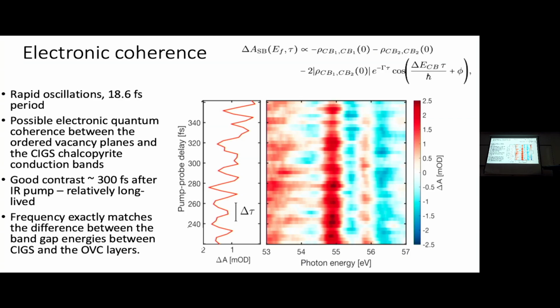It's about an 18 femtosecond period, and it turns out that period exactly matches the difference between the band gap energies of the CIGS and the OVC. So you think, oh, now I'm observing an electronic interference between two band gaps that are slightly different. And this is new. There are very few examples of electronic coherence in semiconductors. And we see it in this material that's submitted in the paper, Physical Review X, and then we're waiting to see what people will say about it.